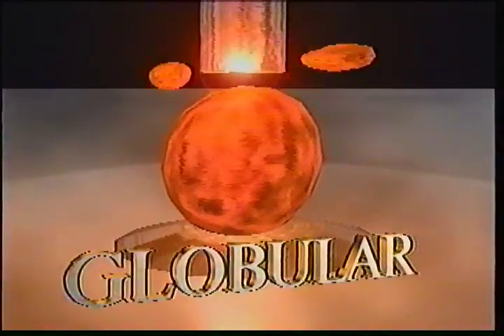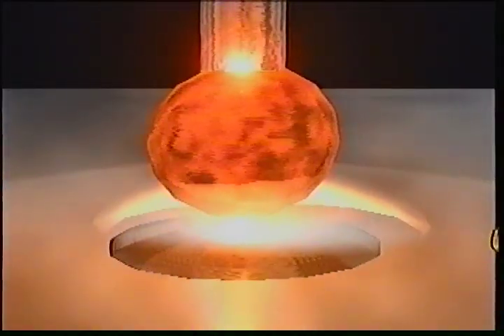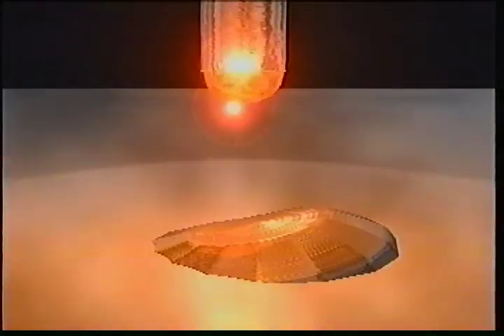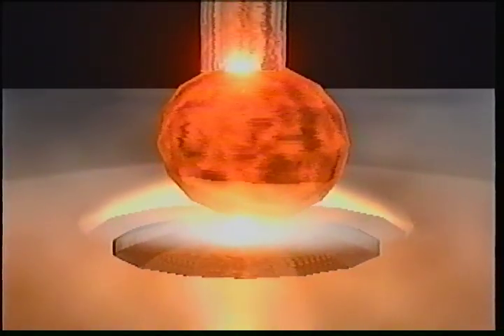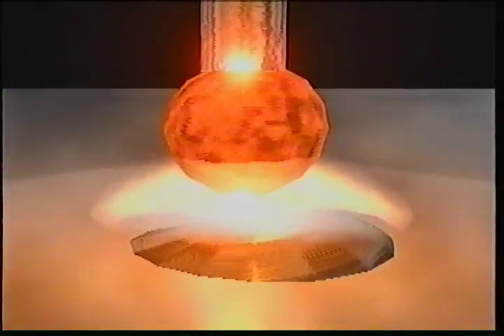During the globular transfer of metal while MIG welding, large globs of weld metal carried by gravity transfer from the wire across the arc to the weld pool. These globs, or droplets, are usually much larger than the wire diameter. Globular is a more unstable transfer with a rough weld bead appearance. The welding parameters, amperage, voltage, and wire feed speed, are higher than for short circuiting. Globular transfer occurs at amperage levels between short circuiting and spray transfer.